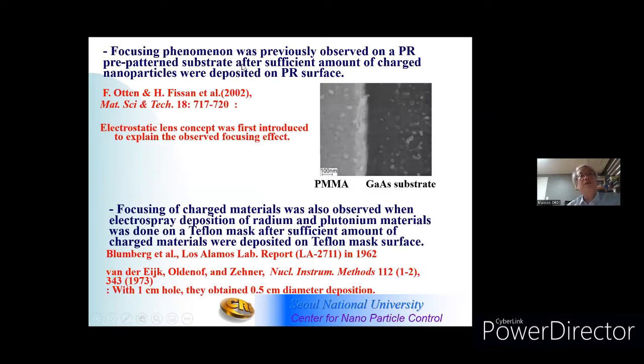This focusing phenomena was previously observed by Fissan's group in 2002 when sufficient amount of charged nanoparticles were deposited on photoresist surface. Here you see this is photoresist opening area. Due to the deposition of the charged particle deposition, there's some focusing effect. There's no particle near this photoresist layer.